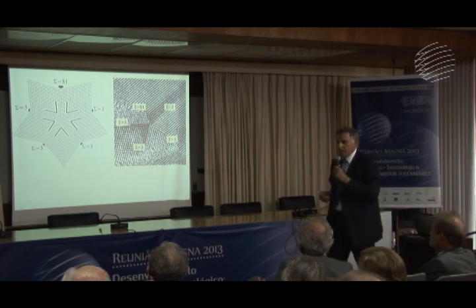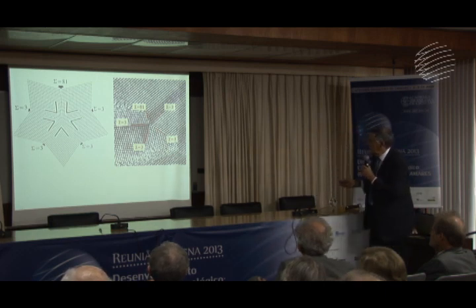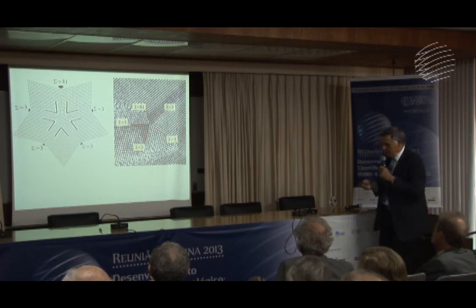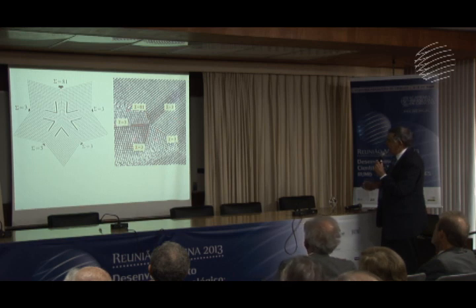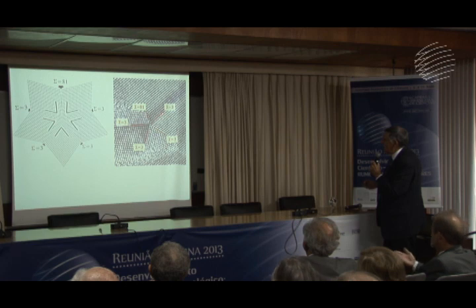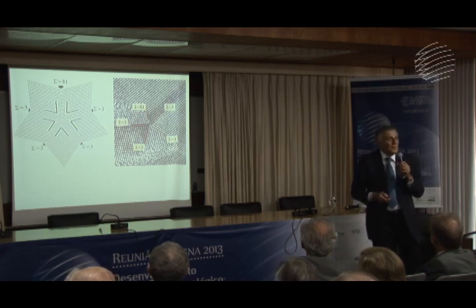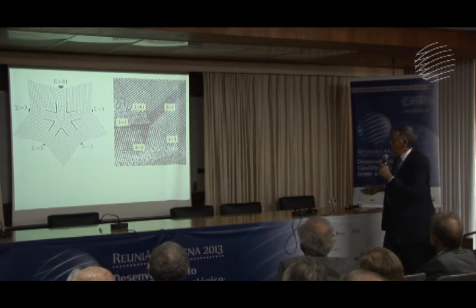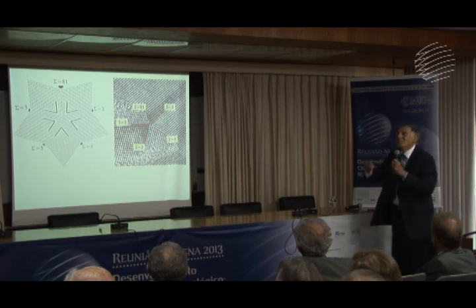What are twins? This is what I thought we have. What you see here are twins in diamond. And these are very special twins. And I will explain what they are. You see, what you see here are atoms, yes? Every bright spot is an atom. This is one crystal. This is another crystal, number 3, number 4, number 5. There are 5 crystals here. Forget about the sigma boundaries. We don't have time for that. So this is one crystal. And this is the boundary. The red line is the boundary between this crystal and this crystal. But the boundaries are not just any boundaries. They are very special boundaries because they act like mirrors. Look here. Look at this. There's some convolution somewhere in the projector.